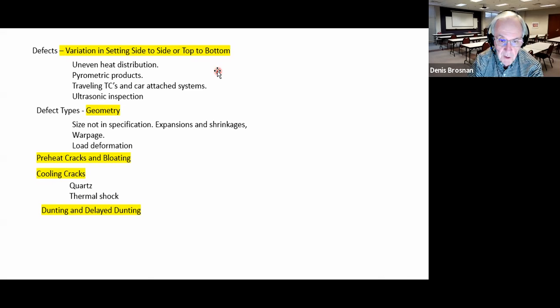Now we have defects by geometry, and that means they may not meet a size specification. Generally, in this course, we've talked about ceramic products shrinking during firing. That's not always the case. They can undergo expansion reactions. In fact, my first job in the ceramic industry was working in research for a company that made products that underwent expansion reactions in firing. They shrank and they expanded. The net result is they came out of the kiln the exact same size that they went in the kiln. Okay, there was no net size change.